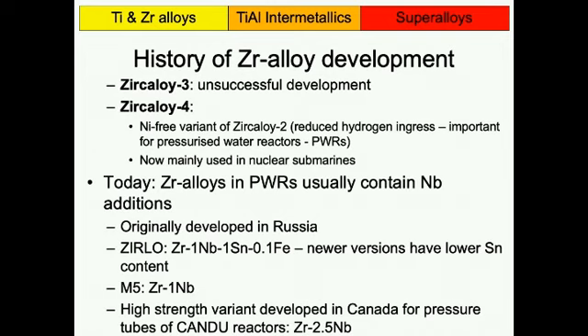So if you now change your material and it goes wrong, you have a bit of a problem, because these submarines, they're quite a few billions of pounds. And the UK, for instance, relies on these submarines from a deterrent point of view, and it's not many of them. If one goes down, there's a problem. So they are very conservative in their approach. Zircaloy 4 is probably not the best alloy these days, but they just find it difficult to have enough data to make that step to a more modern alloy. But in the civil sector,